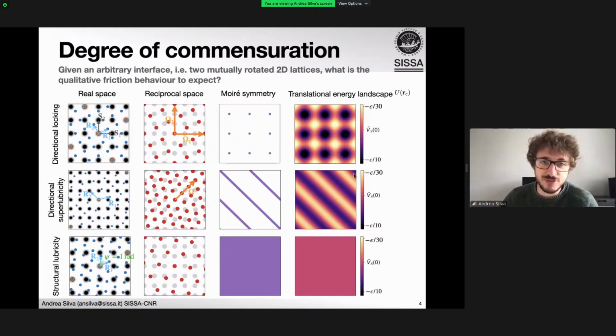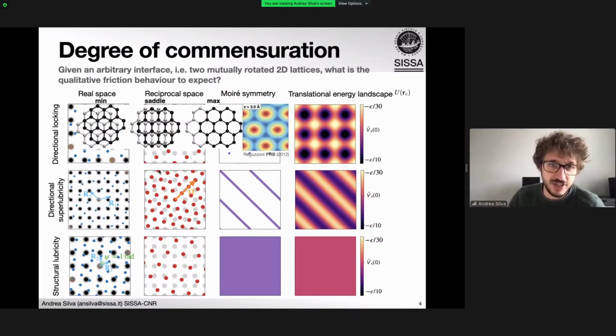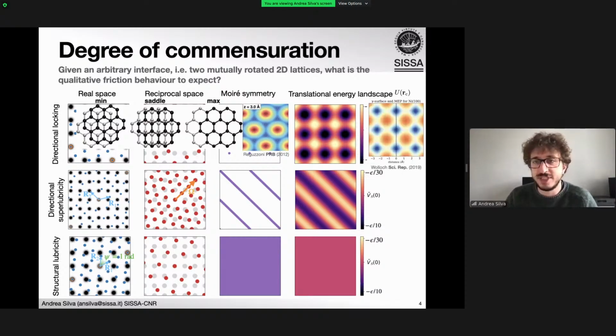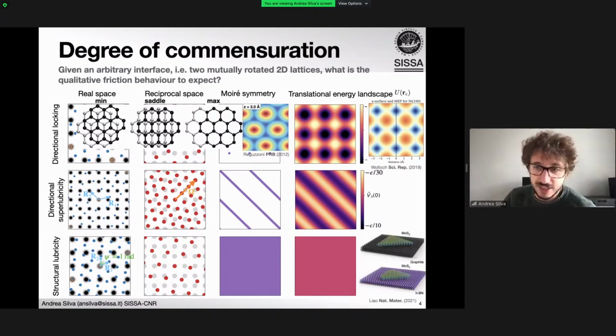And just to go a bit back to the real world, the first case would be the one of graphene sliding on graphene, where you translate the upper layer, you go through different configurations, and you have minima and maxima alternating. Or to give an example with the same symmetry would be nickel on nickel. The case of structural lubricity would be, for example, molybdenum disulfide sliding on graphene or hBN, because they have a large incommensuration. And we are not aware of anyone reporting a theoretical study on this directional superlubricity with this specific friction anisotropy and the scaling law I'm about to show you.